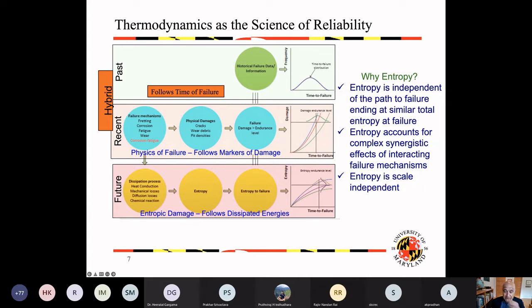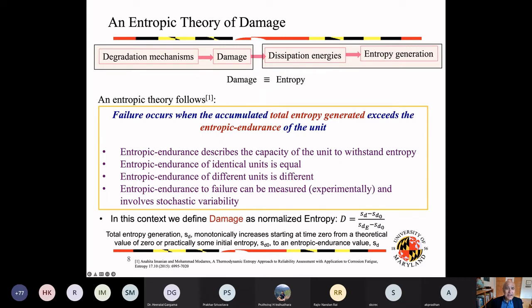The other thing which is very important is that entropy is scale independent, meaning that you could start from a micro level, actually atomic level, measure the amount of entropic accumulation and measure it to the point of end. So therefore, I come to the next definition: failure mechanisms cause damage. Damages generate as they move on. They do dissipate energy, and then they generate entropy. And once entropy reaches a level, it fails.